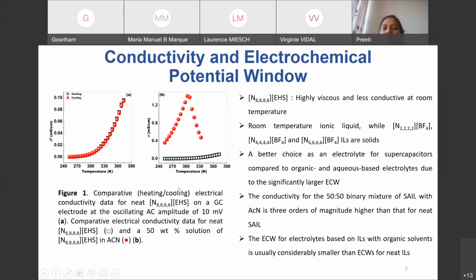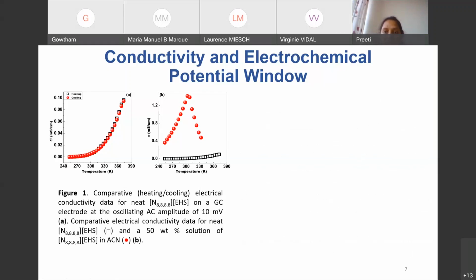Another good thing about this surface active ionic liquid is that it is liquid at room temperature. Whereas if we talk about smaller alkyl groups, like tetraethyl, tetrabutyl, tetrahexylammonium tetrafluoroborate, all these ionic liquids are solids. And we tried with EHS as well. These ionic liquids are solid at room temperature. But interestingly, with these larger alkyl groups, this ionic liquid is liquid at room temperature. Therefore, it is a better choice as an electrolyte for supercapacitors, compared to organic and inorganic solvents, because of the large electrochemical window, which I will show here.